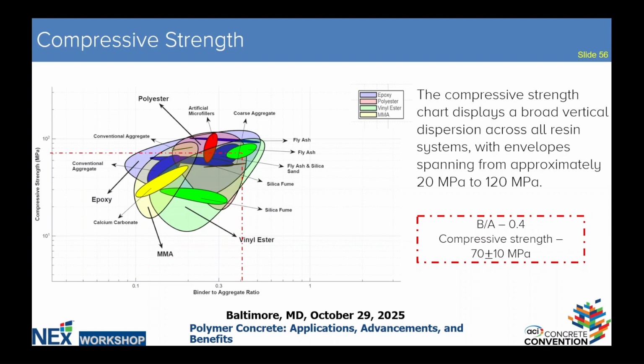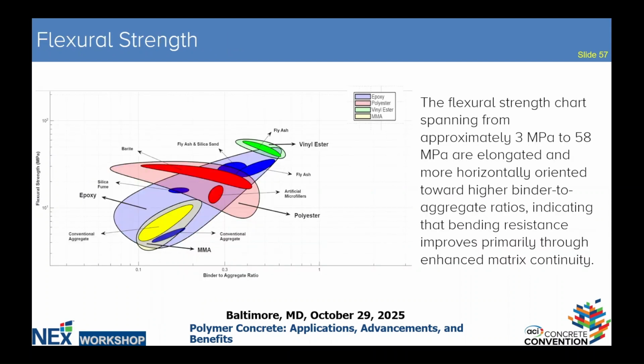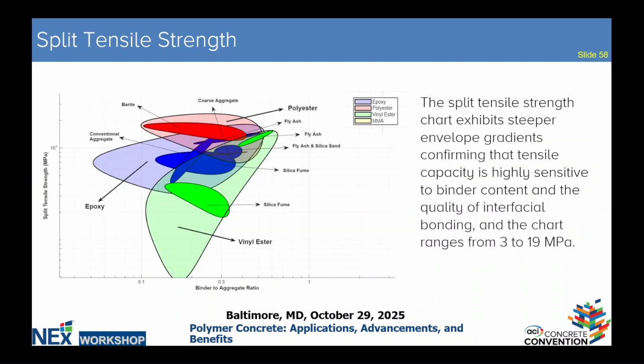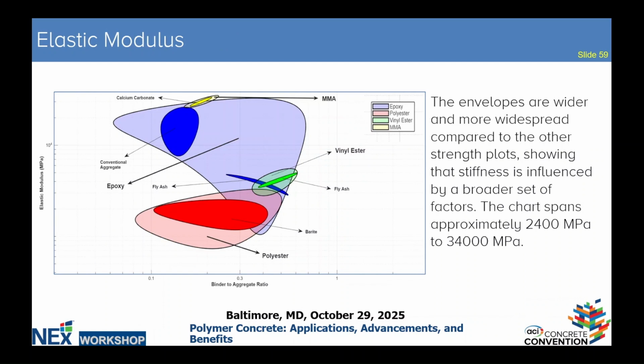Subsequently, we did it for the flexural strength, as you could see how it's more horizontally orientated. So we have the polyester, methyl methacrylate, and the vinyl ester. So just as in the compressive strength data, you just map and also get your flexural strength data in megapascal. And the same applies to split tensile strength, the same mapping. And we finalized on the elastic modulus.